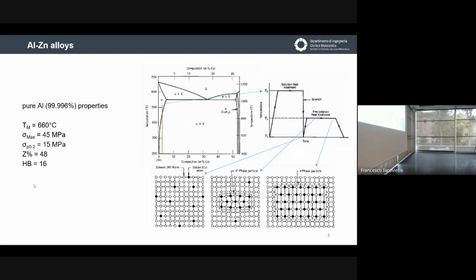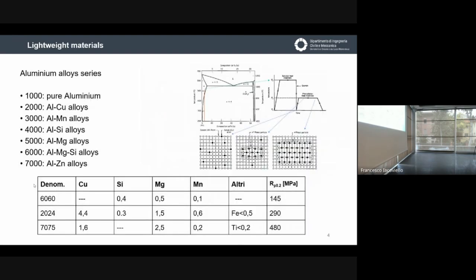Okay. What do I have to do? For example, I can heat the material another time at a temperature lower than the critical one. In this way, the energies are available and the diffusion of the atoms can take place in normal time. What happens? The movement of the atoms, thanks to the lower energy, leads to the formation of these precipitates. How much time do I have to stay at this temperature? The time necessary to grow the precipitated particles, achieving a size that can be comparable with the size of the dislocation. Okay? Which is the result?